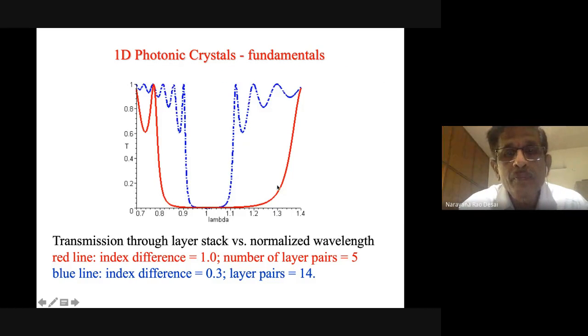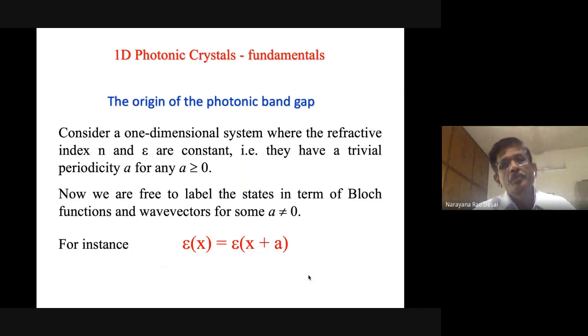This is the transmission, so reflectivity is the other way. Looking at the band gap, this is the transmission. What makes the big difference is the index difference, not the number of layers. For the red curve, the index difference is only 1.0, whereas for the blue curve it is about 0.3, but the number of layers is 14. So it makes a big difference what is the best index contrast that you can get when you make a photonic crystal.